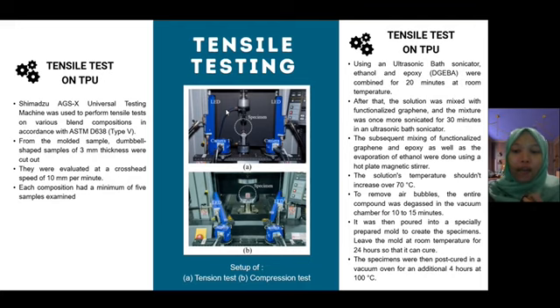It was then poured into a specially prepared mold to create the specimens. Leave the mold at room temperature for 24 hours so that it can cure. The specimens were then post-cured in a vacuum oven for an additional 4 hours at 100 Celsius.